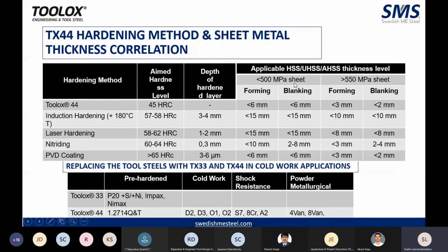If you use less than 500 MPa sheet, and it is less than 15 mm, you can use the laser hardening method. And if your sheet is more than 550 MPa, but the sheet thickness is less than 8 mm, then also you can use laser hardening. So depending upon the tensile strength of the sheet and the thickness of the sheet, you can decide on your particular application.